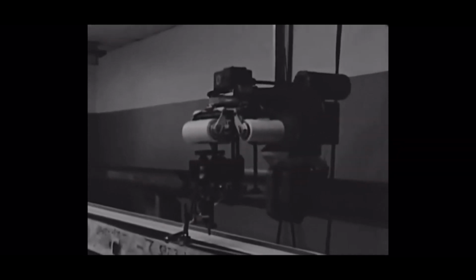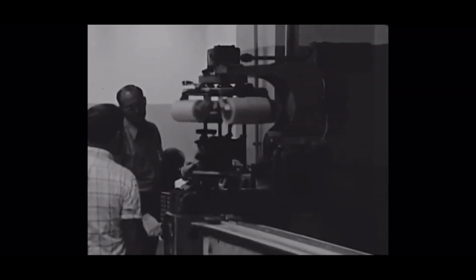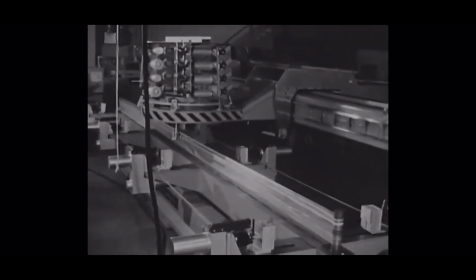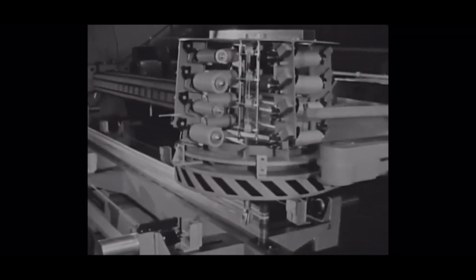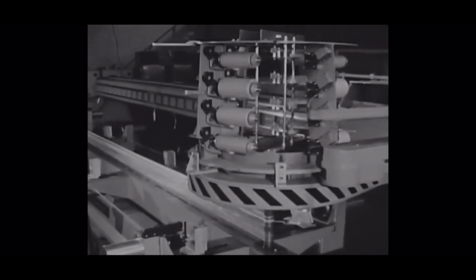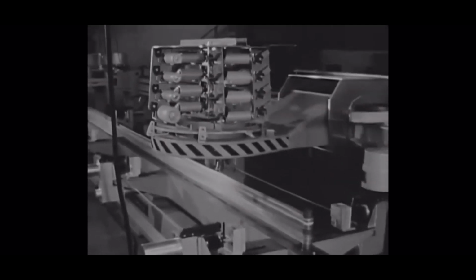Research and development produce outstanding components to increase overall performance and service life. Bell engineers have designed this equipment and are already one step beyond the state-of-the-art in developing fiberglass composite blades using pre-impregnated fibers. The blade consists of a filament-wound S fiberglass epoxy spar with fiberglass afterbody skins supported by Nomex honeycomb core. This filament-wound spar technique eliminates the high cost of hand layup of the composites in the main structural elements of the blade. Fabrication of the blade spar is completed in a single curing operation.